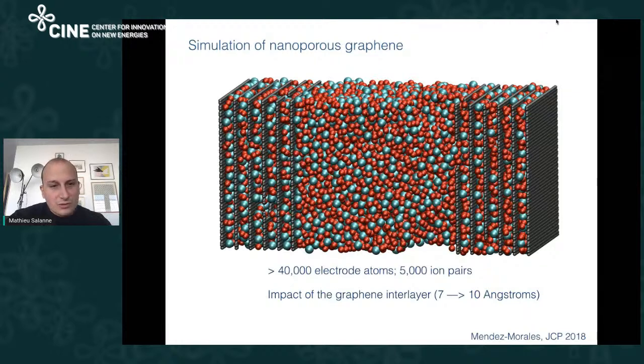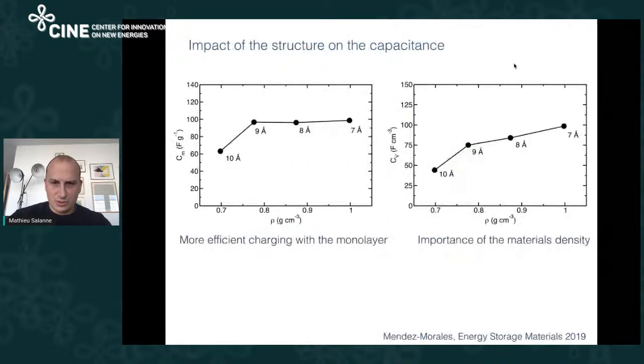What we did, so you see here, there are some holes inside the graphene, so the liquid can go from one plane to another. And what we did is to change the separation between the planes. We switched from 7 to 10 angstrom because we know that's a good range we are interested in, and tried to see what was the impact on the capacitance in particular. And so the results we had are this one. So let me switch to this.